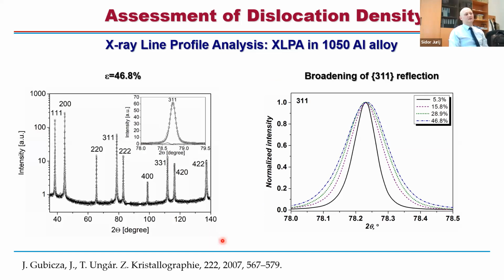Regarding X-ray line profile analysis, there are various groups who developed techniques to assess the evolution of dislocations in various materials by observing or analyzing the broadening of the line. So if you observe, for instance, the 311 line, after a certain degree of reduction, you see virgin material, and then after a certain degree of reduction, you will see that this line gets broader and broader.